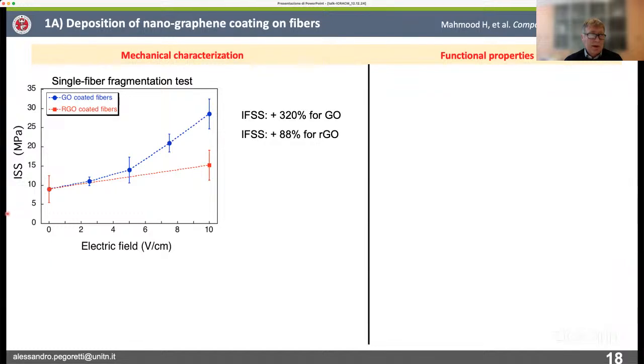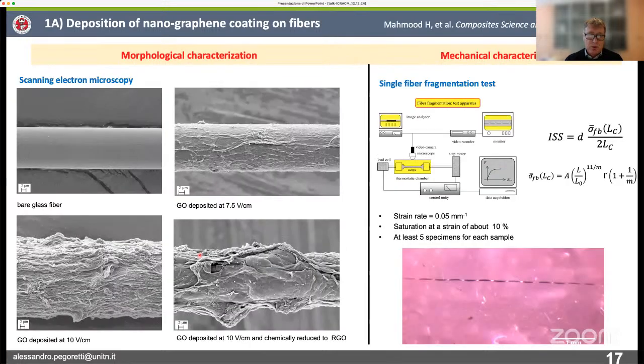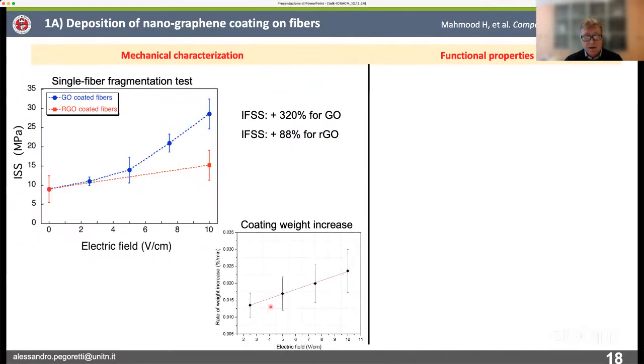If you look at the effect, we can observe a clear increase of the interfacial shear strength when we increase the electric field using the electrophoretic deposition. Just let me point out that an increase in the electric field means an increase of the thickness of the coating, as is actually documented by this data, which reports the weight increase in the tissue, in the fabric that we use under different electric fields. As far as the improvement is concerned, we reach a very high improvement in the interfacial shear strength by more than 3 times by using graphene oxide, and a little bit less, around 88%, by using reduced graphene oxide. And the situation is documented in this plot.